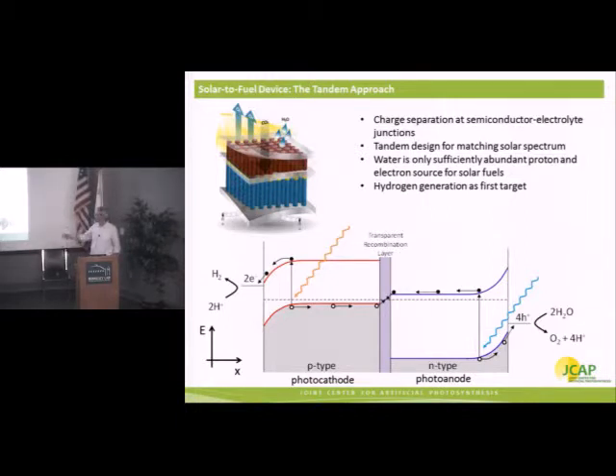These protons are then transported through a conductive membrane to the photocathode side, which operates in a similar fashion, but in this case it's a p-type semiconductor. That means the majority carriers in that material are actually holes. The Fermi level lies closer to the valence band, and under photoexcitation, this electric field at the surface that's generated by the semiconductor electrolyte contact leads to, again, minority carriers. In this case, these are electrons being transported onto the catalyst that's attached to the surface and then forming hydrogen.